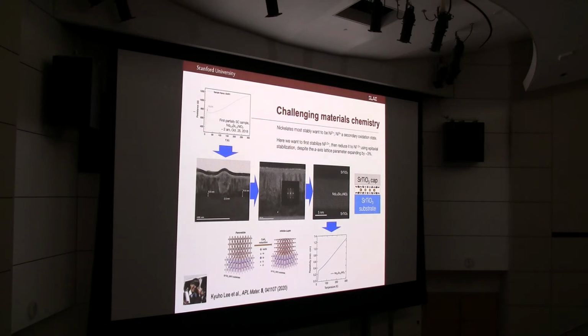So it took us a good part of a year to get to the point where we thought we knew what we were doing and to submit a first paper on this. And this is kind of a snapshot of what happened in between. It turns out that this partial transition was just due to this tiny sliver of material you can barely see right up against the interface. And the bulk volume of the film, the rest of this, is all a mess. It's decomposition, second phase products. You're not supposed to understand more than this looks terrible, and indeed that was the case.